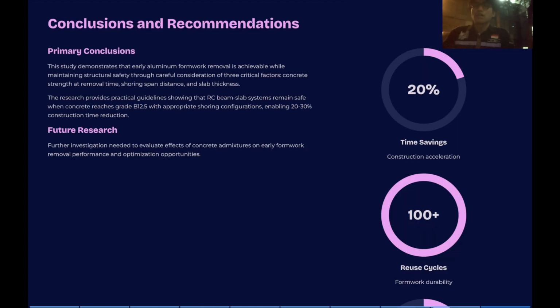In conclusion, early aluminum formwork removal is highly achievable by carefully managing three factors: concrete strength at removal, shoring span distance, and slab thickness. We can safely accelerate construction by up to 30%. For future research, investigating the effects of concrete admixtures to further optimize removal times is recommended. With over 100 reuse cycles possible and 20% value recovery in materials, this system is the future of sustainable, high-speed, high-rise construction. And I think that's all from me.